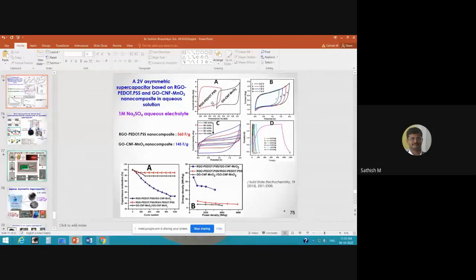In this case, the hydrogen evolution will be avoided on this side, and the oxygen evolution will be avoided by using this side. So when you have a manganese oxide, you can avoid the oxygen evolution. When you have this configuration, you can avoid the hydrogen evolution. So by combining these, you can extend this potential window up to 2 volt without any hydrogen and oxygen evolution. But it is a tricky process.